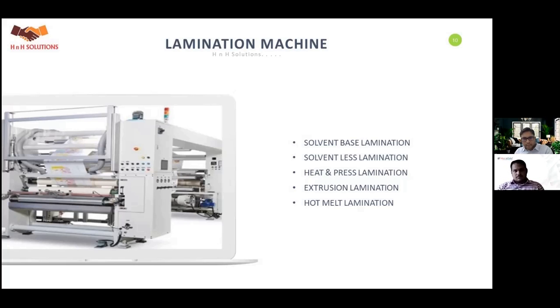Then heat and press lamination for pharma foil, extrusion lamination for bulk bags like cement, rice, wheat, granules, and we can produce material for 10 kg, 20 kg, 25 kg, 50 kg, and up to 1000 kg bags. Then hot melt lamination for soap wrappers, cold seal lamination for confectionery, chocolates, and low melting point products.